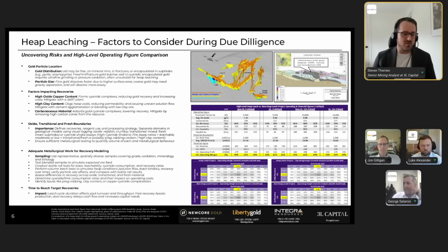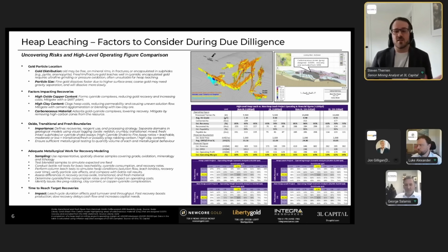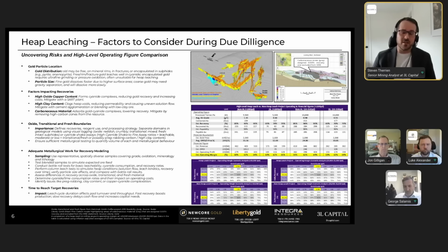So your oxide, your transitional, and your sulfide domains. Each one of those is going to have different recoveries, different recovery curves on column tests and in the real world. These things can be separated out in your model, based on visual core logging. You can use cyanide shake assays and look at the ratio between the cyanide shake assay value and the fire assay. If you have high ratios, that's a good sign that you have leachable oxide material. If you have, let's say, 0.3 to 0.7 ratios or less, in that range, maybe it's transitional. And if you have less than 0.3, that could indicate fresh rock, or maybe you have some preg-robbing carbon.